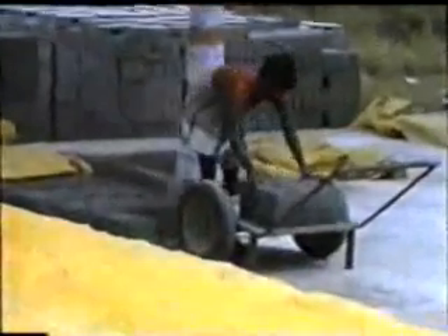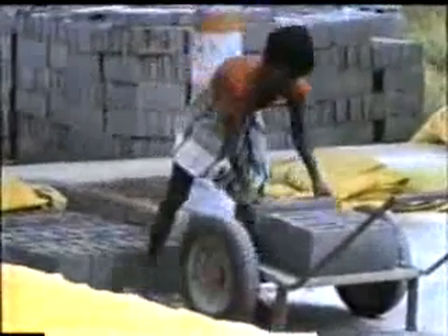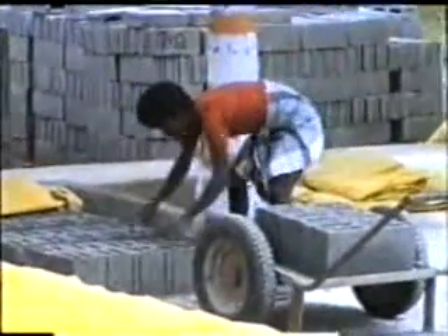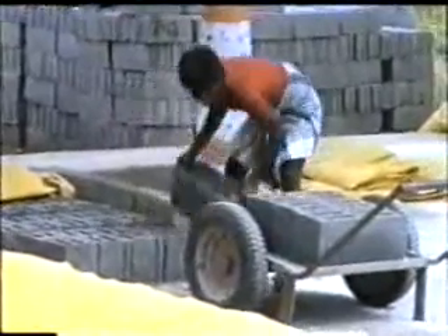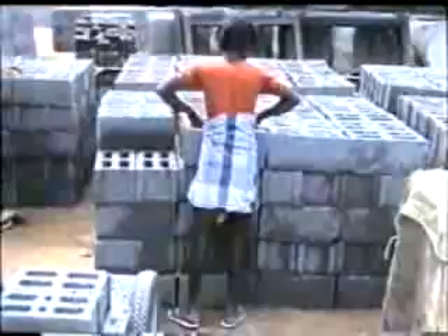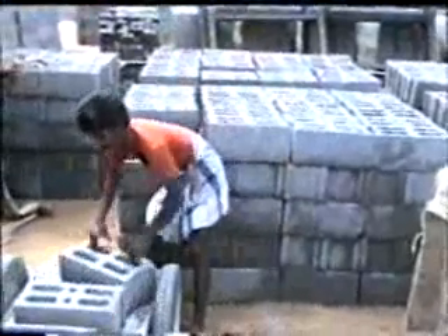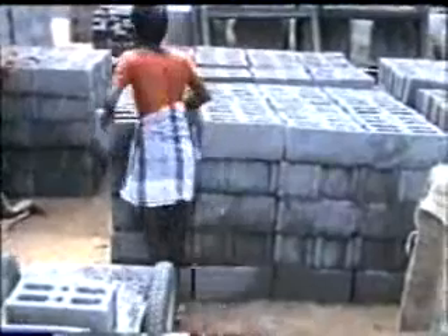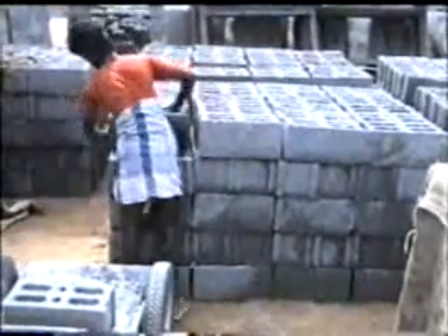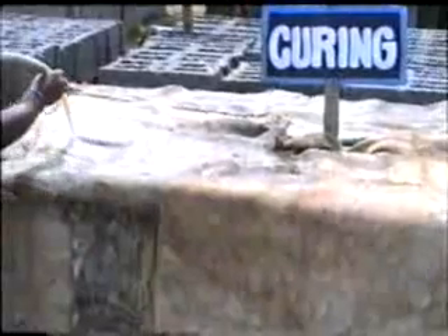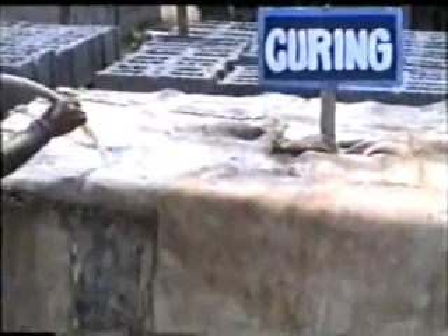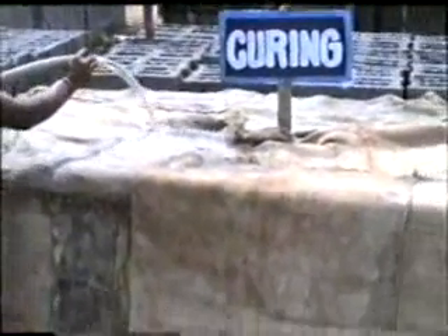The third step is the curing stage. Blocks are then covered with a plastic sheet to protect them against sun and strong winds. They are kept like this for 12 to 24 hours until they have sufficiently hardened to permit handling. After 24 hours, the blocks are placed in a stack and covered by jute gunny bags. Water is poured over the gunny bag for a period of 14 days.